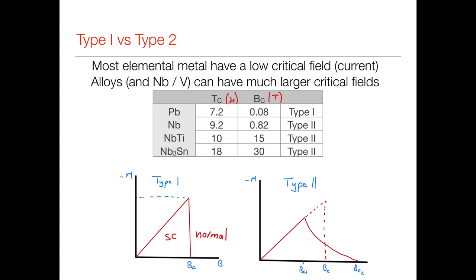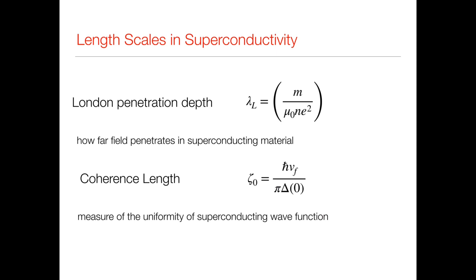Now, we need to try and understand what the difference is between a type 1 and a type 2 superconductor from the theory that we have. And actually, there are two different length scales that are important in superconductivity, which come out from BCS. They also come out from this Landau-Ginzburg model. And one of them we've met already, and that's the London penetration depth, lambda given here. And this tells us about how far the magnetic field penetrates into a superconducting material.